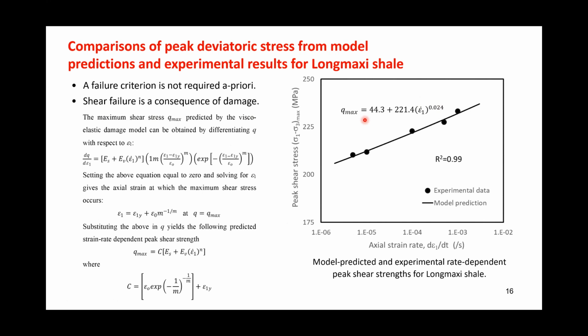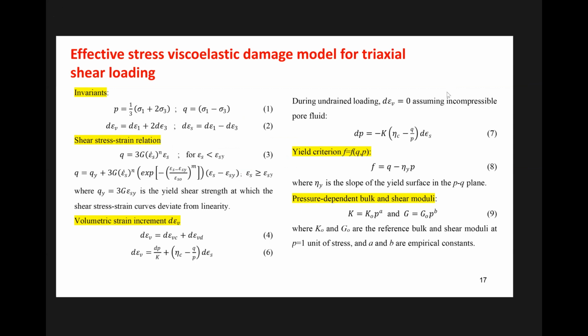Substituting it back, we get this stress-strain relation. These are the experimental points, and you can see the model prediction is excellent with an R squared of 0.99. So again, the failure was not prescribed, it was not necessary a priori. You don't need it at the start. It's just an outcome of the damage of the material. So the peak in the stress-strain curve is properly predicted.